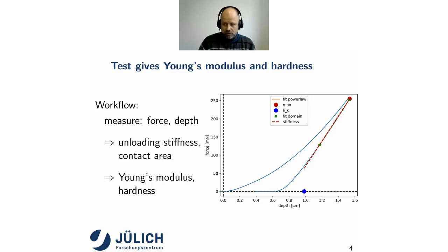Just as a reminder for those that have not done these theory questions before, typically you measure the force and the depth. From the force and the depth you can calculate the unloading stiffness. From the unloading stiffness you determine the contact area. These are both evaluated, and from the contact area, then you know the Young's modulus and the hardness.